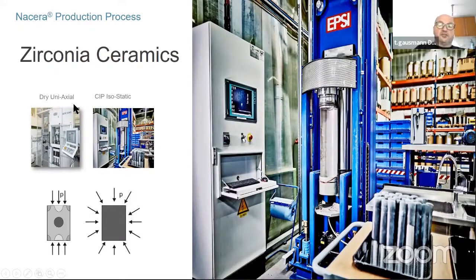It's a dry uniaxial pressing in a normal press. The powder goes into a mold and is pressed from the upside and the downside together. This is not homogeneous. You can see here a dark spot, medium colored spots here, a different size spot here, so nothing is homogeneous in the first pressing. You need a lot of pressure to make it nearly homogeneous, and still it is not perfect. So we, like many other companies, go to isostatic pressing. In isostatic pressing, the disc is put by hand into a bag, sealed under vacuum, put into another bag and sealed again, and then it's put into a water tank. This water tank is put under a pressure of 3000 bar.